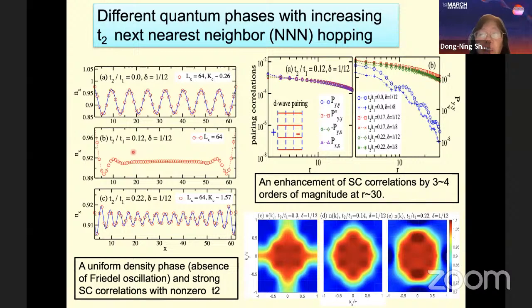With increasing T2 over T1, we go into a quantum phase where the electron density in the bulk is very uniform. Only at the boundary you have a small boundary effect. We don't have this usual Friedel oscillation for this fermionic system.